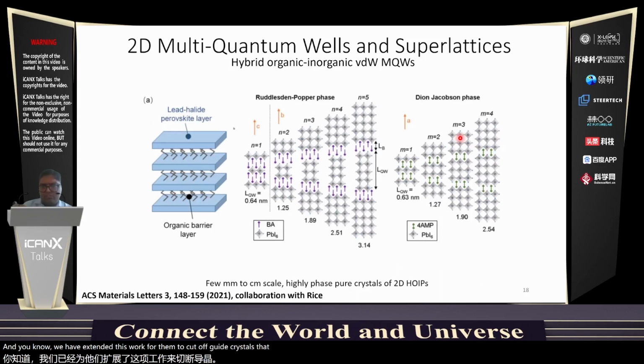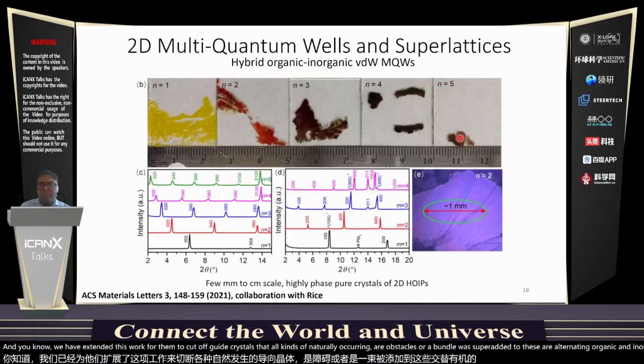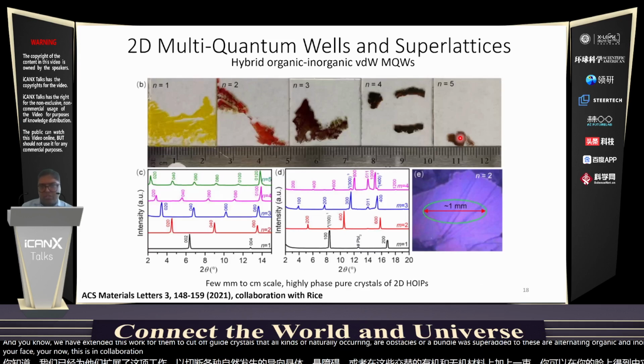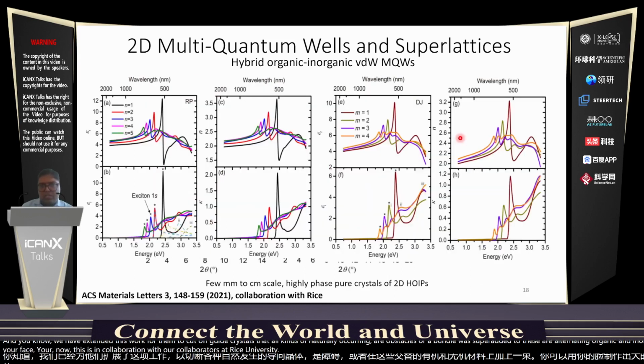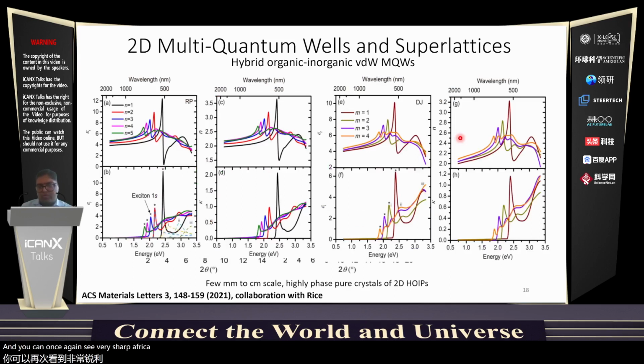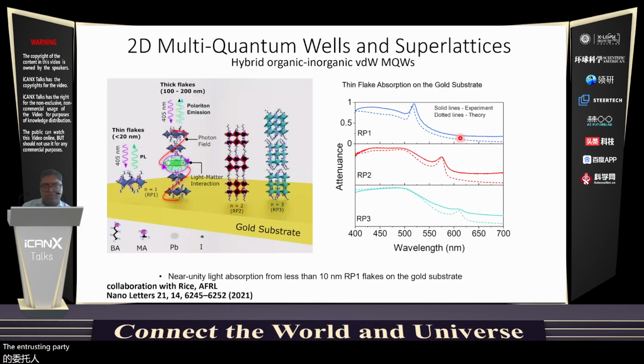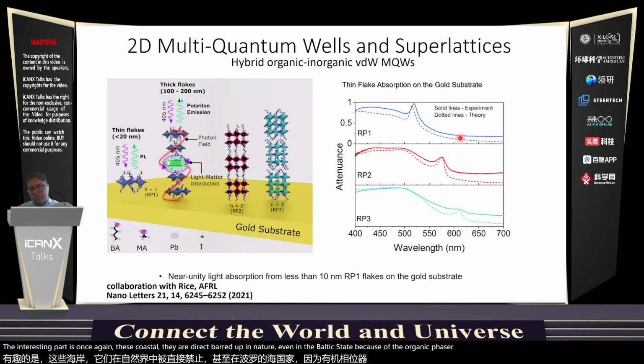We have extended this work further to perovskite crystals. Perovskites are naturally occurring optical or van der Waals superlattices. These are alternating organic and inorganic materials. You can get large crystals made out of them, which are phase pure now. This is in collaboration with our collaborators at Rice University. And you can once again see very sharp optical resonances in these materials if you take spectroscopic ellipsometry. The interesting part is, once again, these crystals are direct band gap in nature, even in the bulk state, because of the organic spacers. The organic spacers prevent enough separation of the wave function in individual layers that they retain direct band gap.